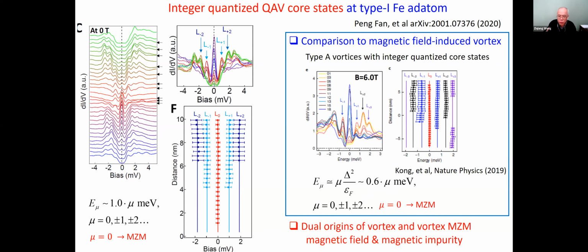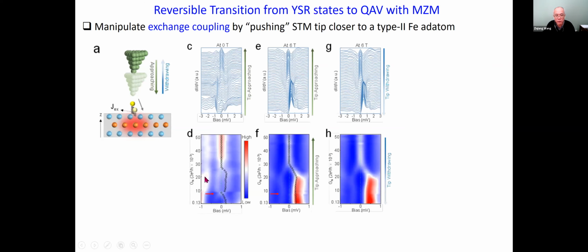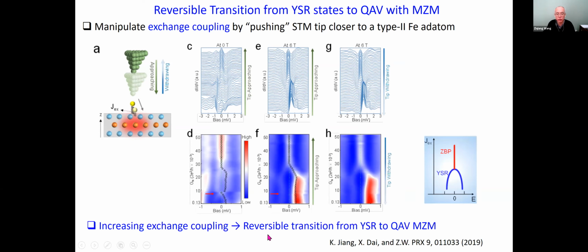So therefore, I hope this proves there's a dual origin of the vortices and vortex Majorana zero modes in iron-based superconductors with topological surface states. They can be induced by magnetic field or by magnetic impurity. And I won't have time to say this, but I'm just going to flash this. They could actually use the tip to turn an iron impurity that only shows Yu-Shiba-Rusinov states, and you can push it in so that the state collapses and turns into a single zero energy state. And this is a transition. In fact, it's also reversible from Yu-Shiba-Rusinov to the quantum anomalous vortex state.